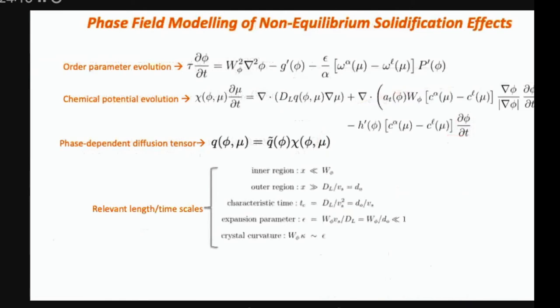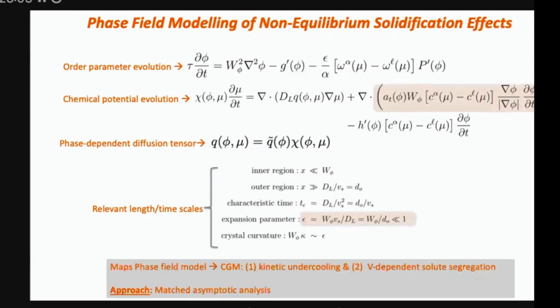And so a few years back, what we did is we re-ran this so-called asymptotic analysis of the phase field model to say, okay, what do you have to do to the model parameterization so that when it's doing its thing, the interface emulates not local equilibrium, but local non-equilibrium based on the model that I just showed you. And what we did was we have to add something known as an anti-trapping flux. It's an extra non-variational source term to the mass transport equation that essentially slows down the diffusion enough in the interface so that solute doesn't have time to diffuse and it gets trapped in the solid according to some prescription of this model I showed you before.